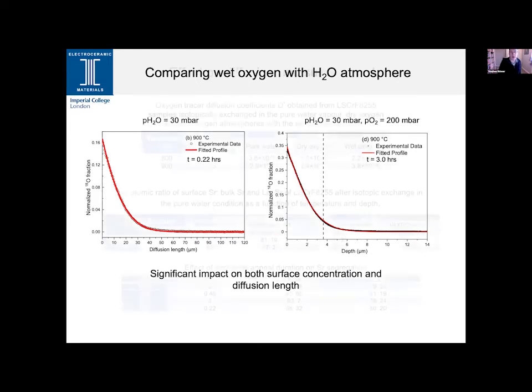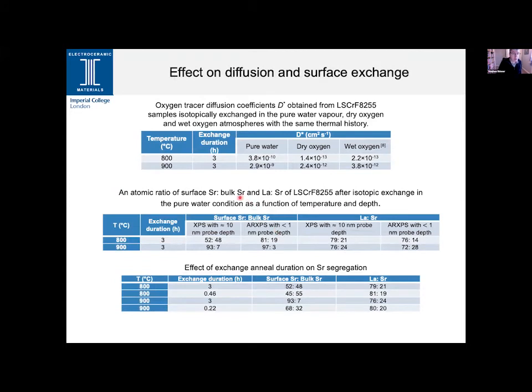If we move forward from there, there are a few tables now, I'm afraid, so I'll point out some of the key features. Now we have the comparison between the pure water, the reducing condition effectively, the dry oxygen and the wet oxygen, looking at the oxygen diffusion transport parameter, and we can clearly see that the dry and wet oxygen are of the same order of magnitude, 10 to the minus 12 at 900 degrees C, 10 to the minus 13 at 800. Whereas in the pure water, we've got about a 2 to 3 order of magnitude improvement in that diffusion coefficient. Again, this reaffirms the initial data that we had in that 120 millibar system.